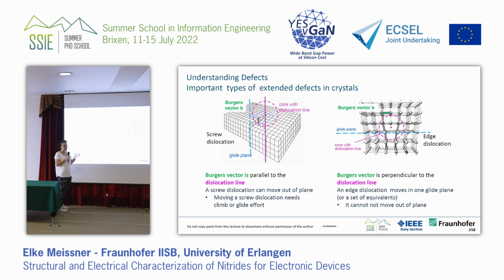It means that you consume space where there was nothing planned for in the lattice. So you create a strain field. This is what you do. You can characterize the dislocations by the geometry of the line vector and the so-called Burgers vector. The Burgers vector is the displacement vector. This is really where the lattice is displaced, in a measurable number. The Burgers vector and the dislocation line are perpendicular to each other by definition for an edge dislocation, and for a screw dislocation, line vector and Burgers vector are parallel.